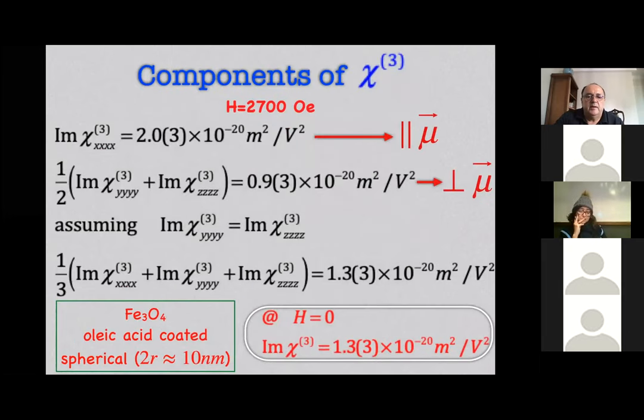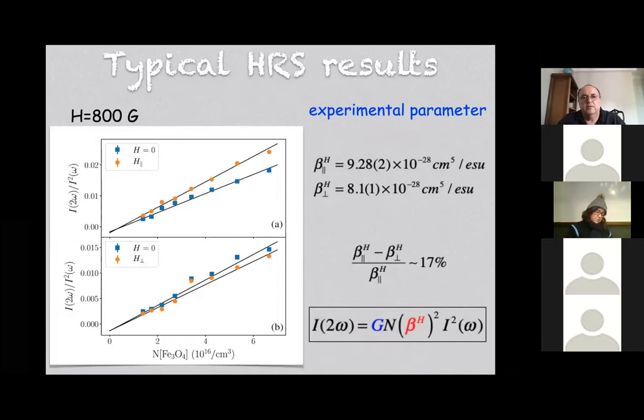And the components of Chi3 that we measure for the magnetite particles here, as I told you, the imaginary part of Chi3 is related to beta, and the real part of Chi3 is related to N2. So this is the direct measurement of this anisotropy along the direction of the magnetic moment or the external applied magnetic field. On the other line, or perpendicular, we have a mean value between these two Chi3 along Y and Z direction. But if we assume that they are not so different here, it is interesting that if we calculate with this value what we would expect in the case of no magnetic field applied, we have essentially the same value. So it seems that this assumption we did here is reasonable, it's not too far from the reality.